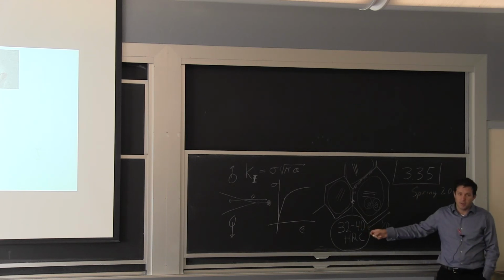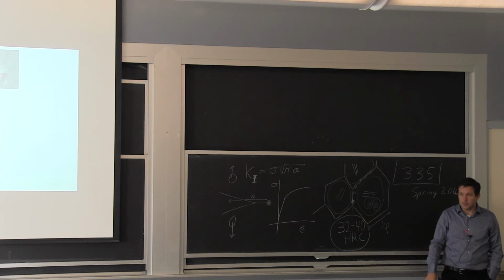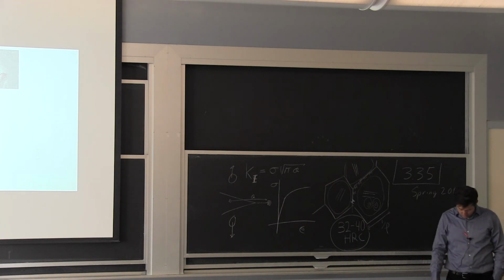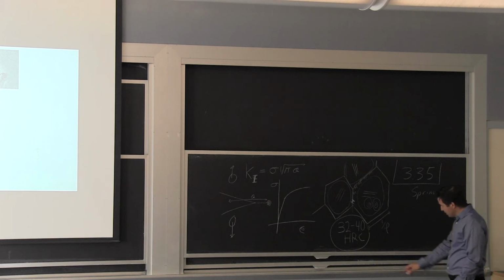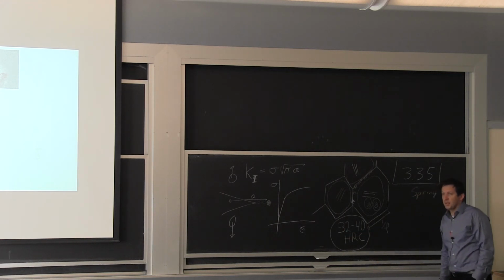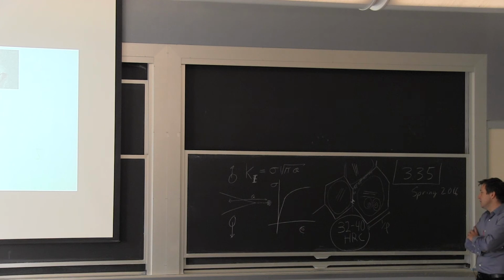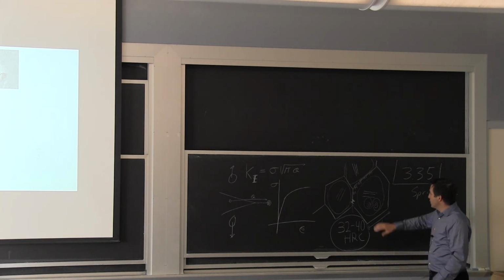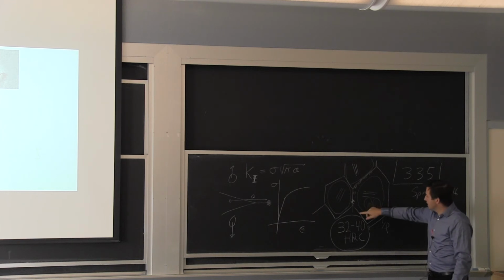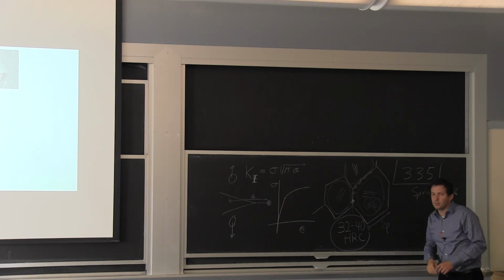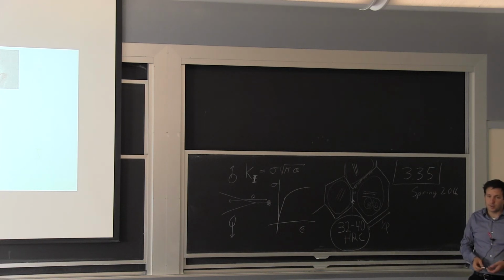Some I've seen before, some manufacturers target 40, and those are some of the things that are circulating around. They did fail in the brittle manner. So closer to the lower end is what you would normally want to do. I've seen in the oil and gas industry maximum hardness of the order of 32, sometimes up to 35 Rockwell C, just for that reason, for trying to make sure it's going to deform here as opposed to have the decohesion on the grain boundary because of small elements like hydrogen segregating in there.